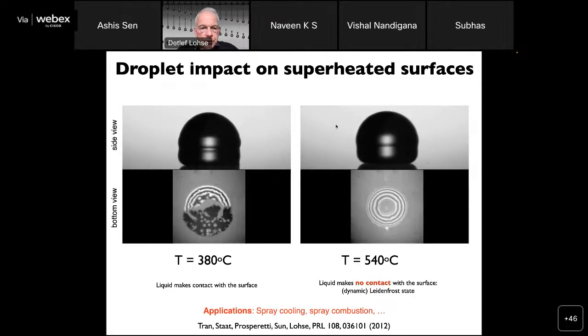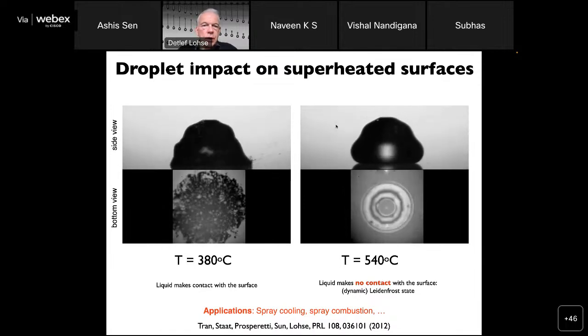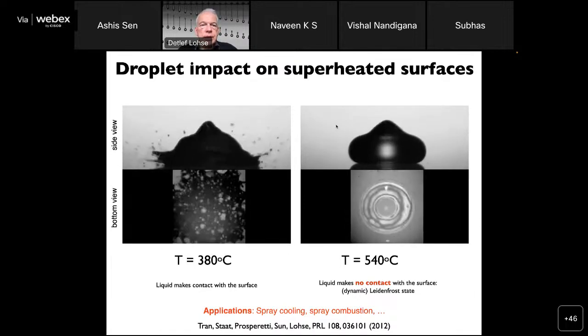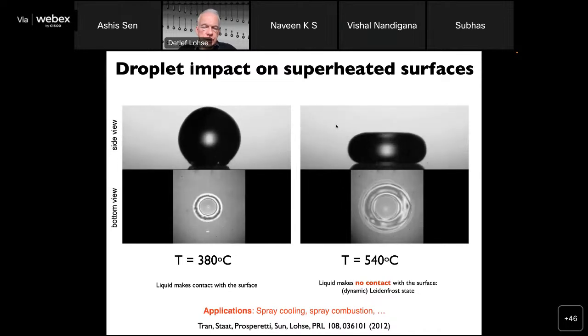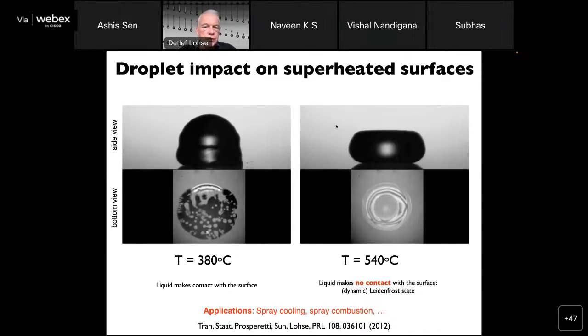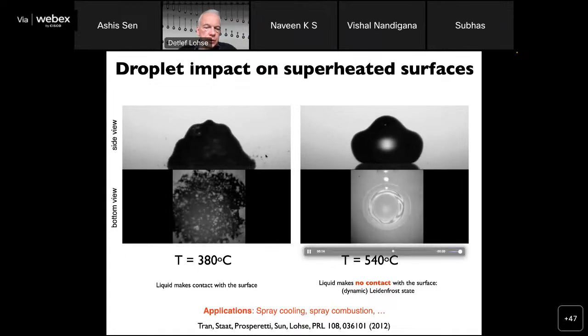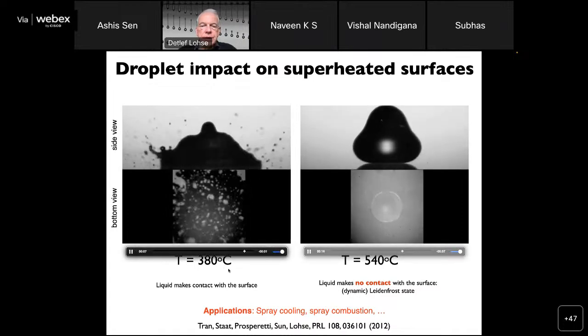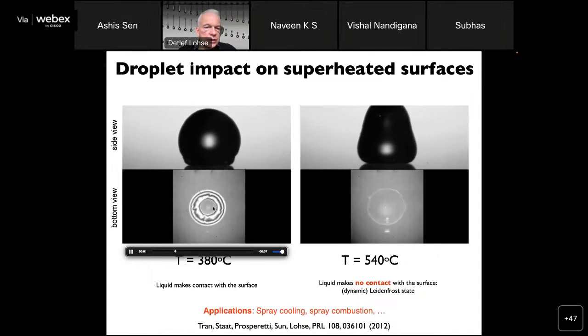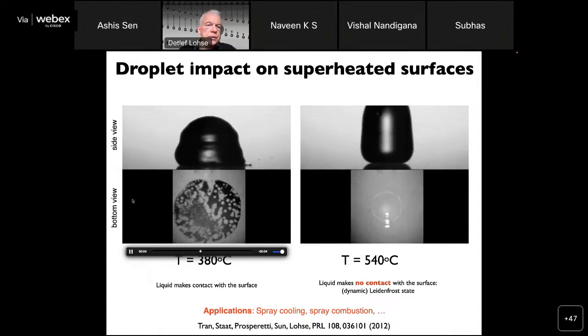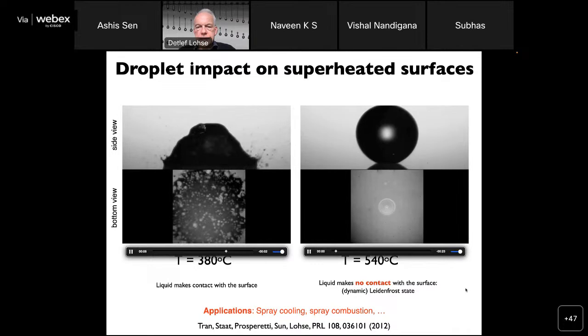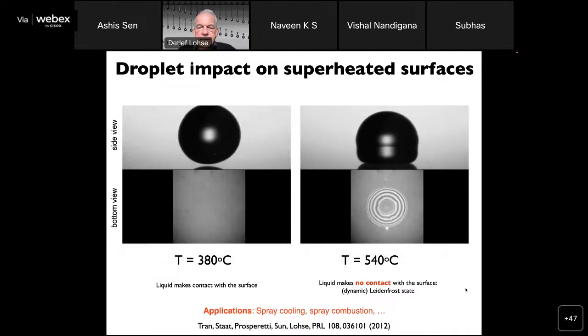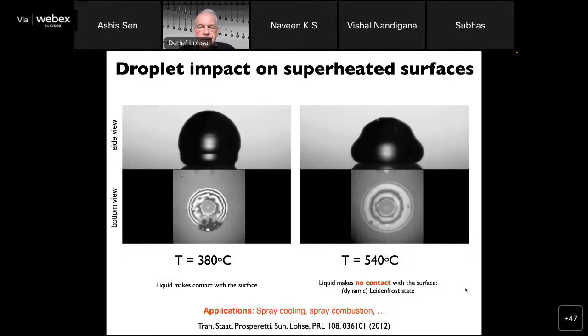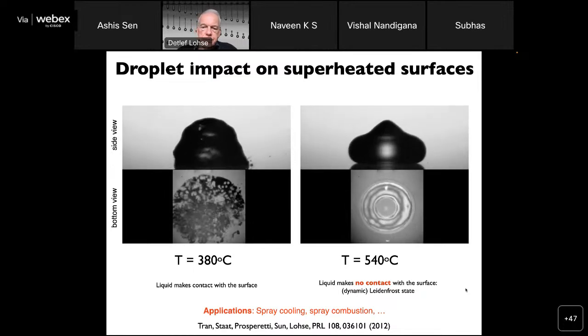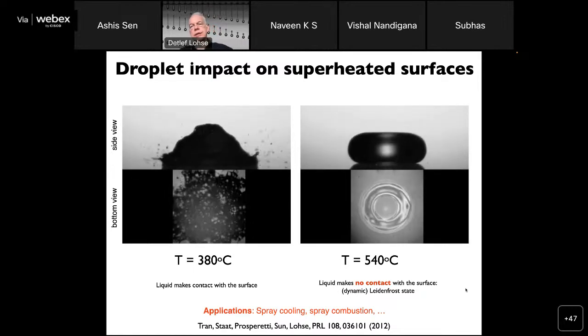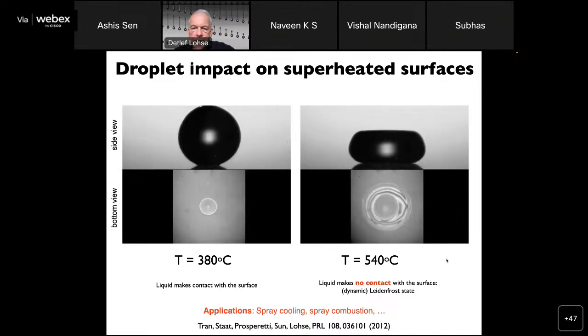And this is what you see here. So up to now we had supercooled droplets. Now I have superheated surfaces, and I let droplets fall on it. And on the left, you see a droplet falling onto a surface of 380 degrees. And then you have touchdown and boiling. So here's the side view and the bottom view. Whereas on the right, the temperature is higher. It's 540 degrees Celsius. And there the liquid doesn't make any contact to the substrate. So here we have the dynamic Leidenfrost state,